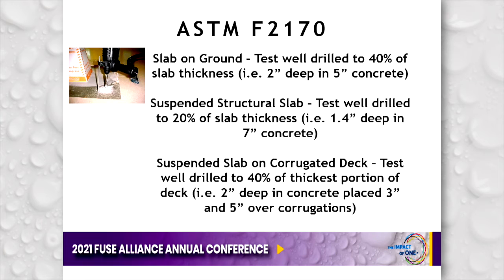7-inch concrete slab. And then the suspended slab on a corrugated deck. Again, this has been done incorrectly for a long time. It is now specifically written in F2170 that we are to drill to 40% of the thickest portion of the deck, regardless of where we drill the hole. So if we have corrugations that cause our concrete to be 3 inches thick over the corrugation, 5 inches at the bottom of the corrugation, we want the test well drilled to 2 inches, regardless of where on that slab we are drilling the holes.